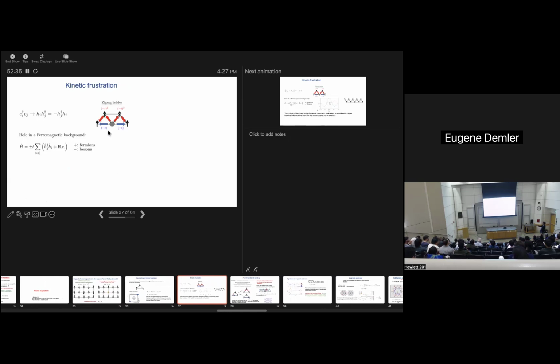Let's consider a triangle. Now let's start with a spin polarized system, introduce one hole, and look at the motion of the hole. First of all, we want to change the system from hopping of electrons to hopping of the hole, because we have just one hole. But this, of course, exchanges creation and annihilation operators. Now, if we want to put the operator for the hole back into the right order, we see that we acquire a minus sign. So for the hole, as we make the transformation, hopping changes sign.